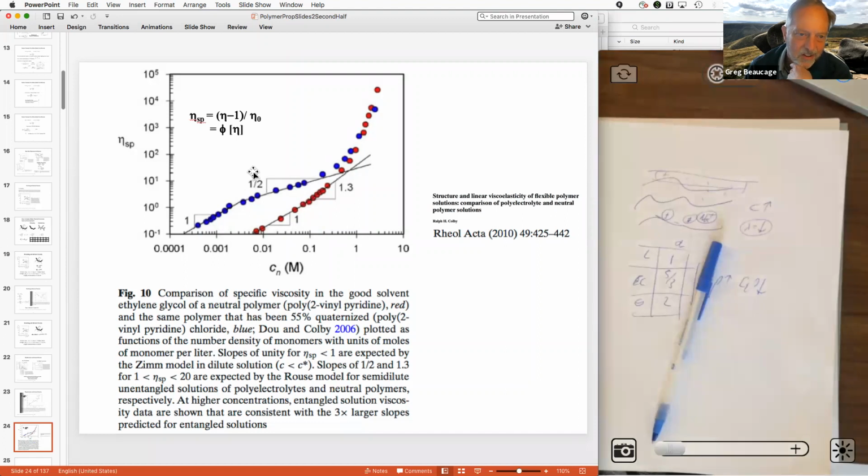So you can get a transition between a linear chain and polyelectrolyte to try to show that this transition regime between the overlap concentration and the entanglement concentration has different slopes for the two polymers. And that once you get this total screening, the two things are the same, because the red ones already with salt added, the blue one with salt comes from the counter ions for the chain. Then they match at the high concentration. So this is a pretty nice paper, 2010, where he kind of demonstrates this stuff more or less for the first time. So why don't we quit there?